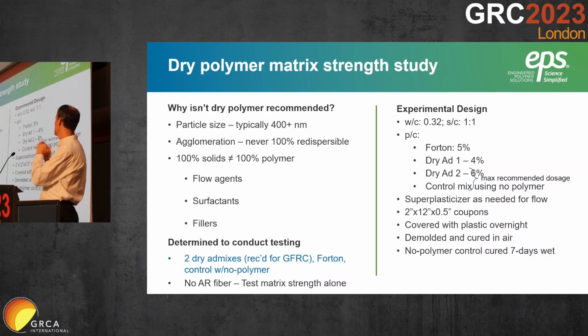So experimental design: we used a water to cement ratio of 0.32, sand to cement of 1:1, and polymer to cement. Forton, we put it at 5%. That's what we recommend. The two dry admixes both had a maximum recommended dosage, so we put in what they labeled as their max: 4% of one, 6% of the other, as they directed. Then we had a control using no polymer. We added superplasticizers as needed for flow.